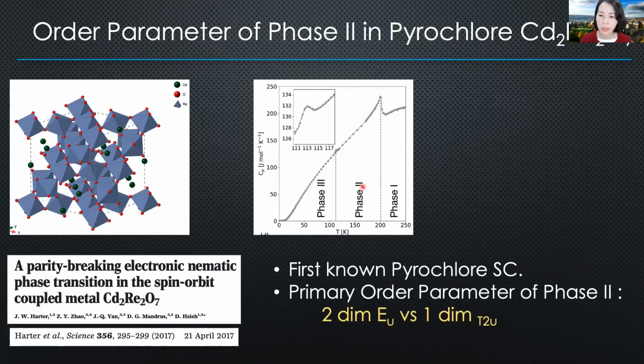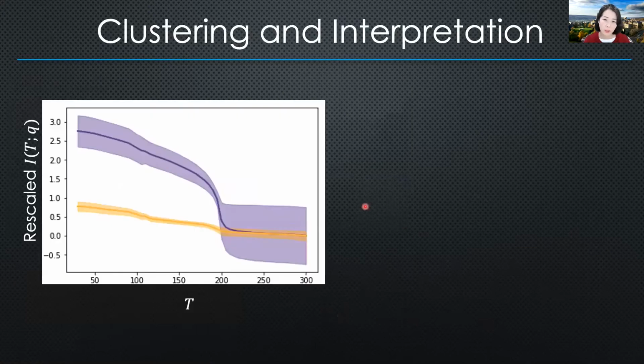The difficulty is that these are structural transitions with extremely small distortions. And the big puzzle has been whether this phase should be described by a two-dimensional Eu order parameter or a one-dimensional T2u order parameter. So together with Argonne National Lab colleagues, we have analyzed about 8 terabytes of data. And the whole 8 terabytes of data spanning 100,000 Brillouin zones gets captured by our X-Tech into this simple form.